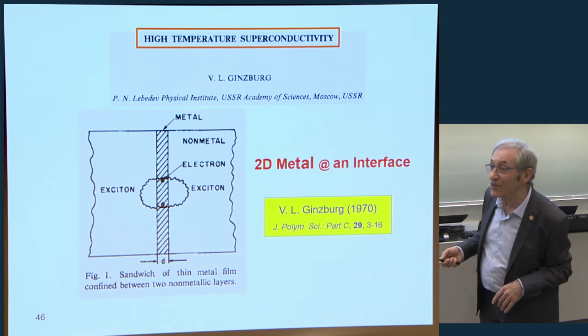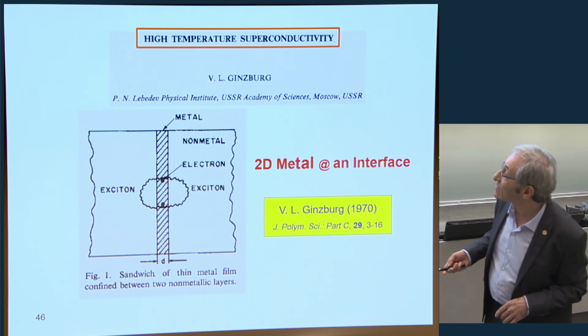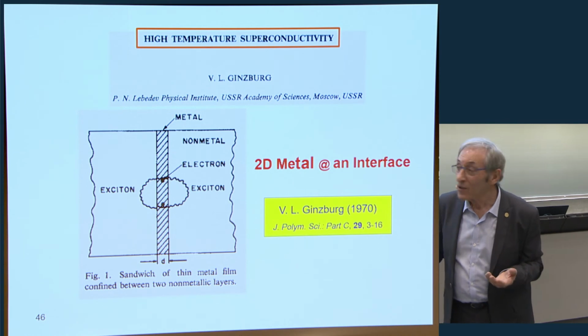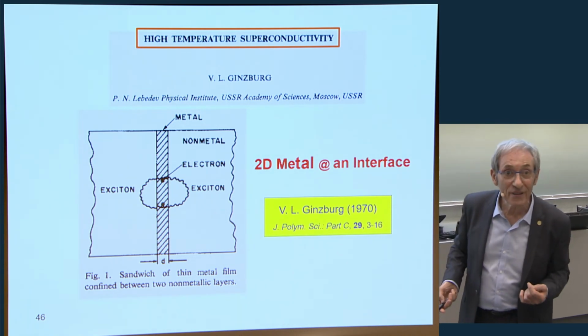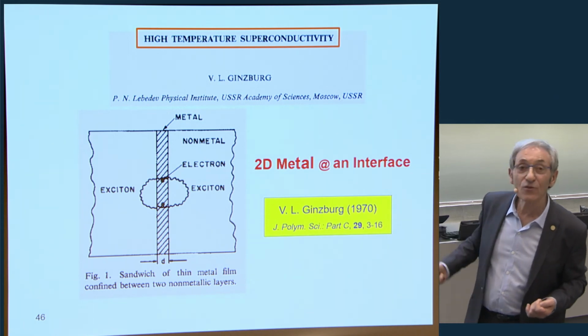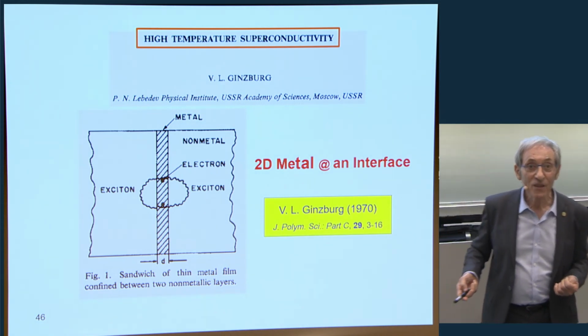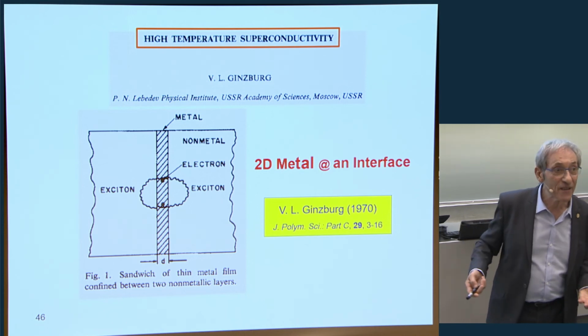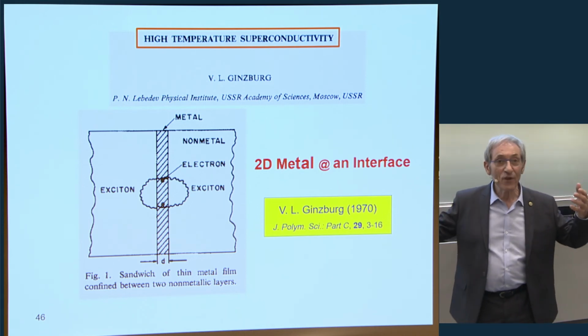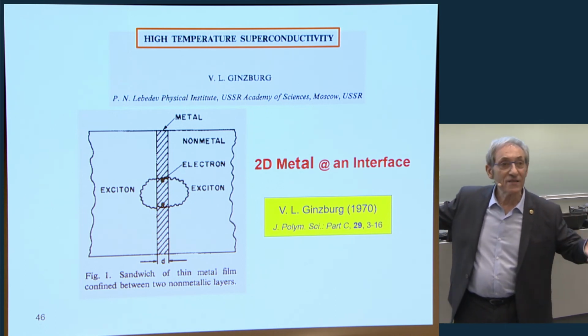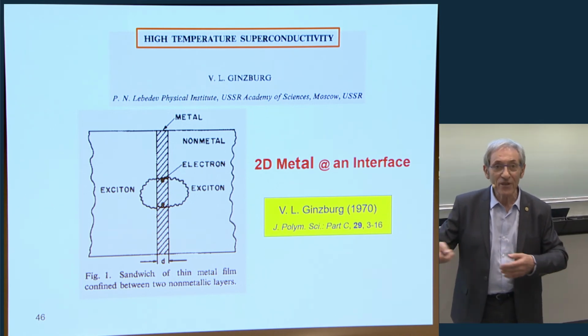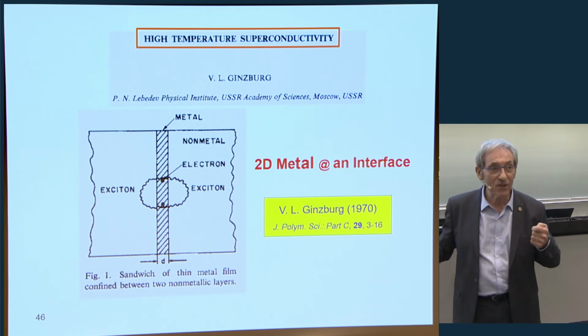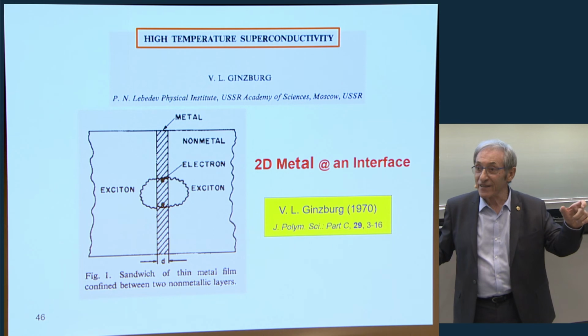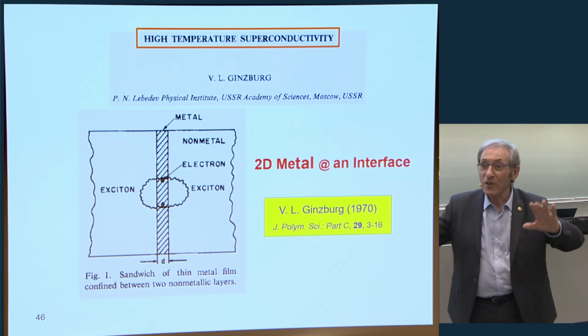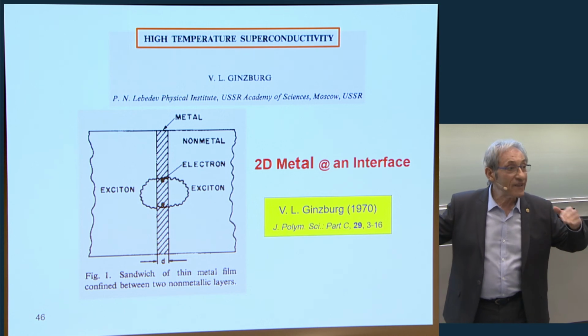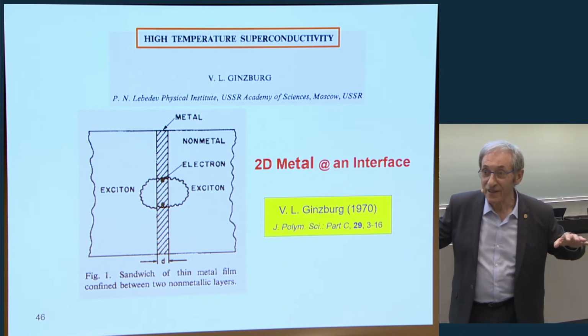And a similar theory proposed by Ginzburg is to use a two-dimensional metal with a thickness of not more than 1 nanometer between, let's say, two semiconducting materials that provide this same mechanism of exciton coupling. So now we start thinking that what we have is exactly or very similar to this. We have something that is between one-dimensional and two-dimensional. By the way, the high conductivity is only on the nanoscale. If we make them much wider and with much more silver, then they become regular conductors with conductivity poorer than the bulk silver. So that's the point.